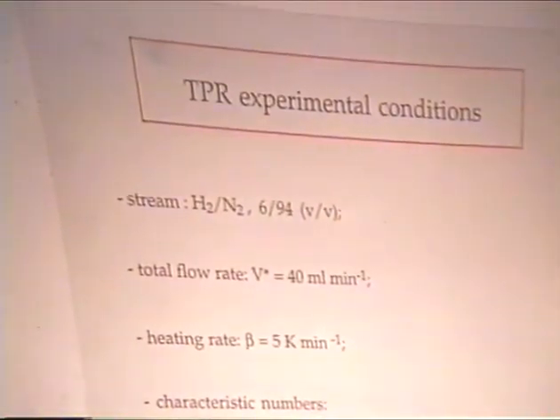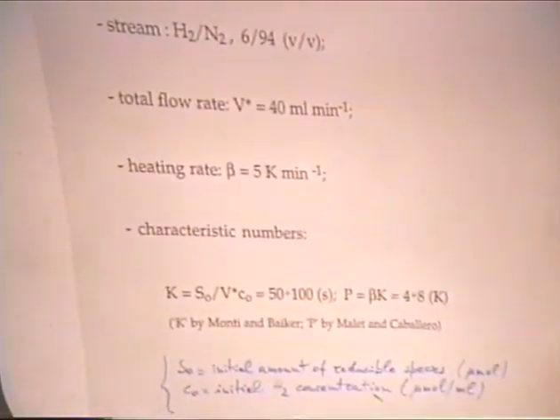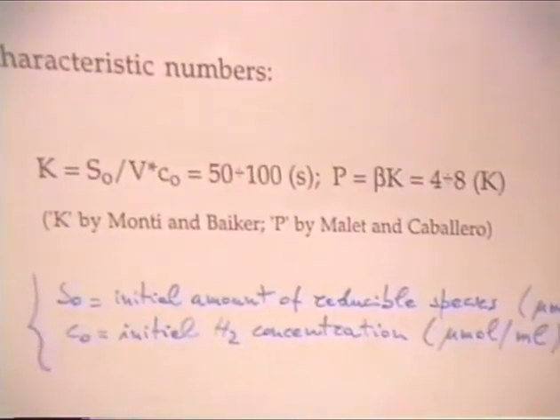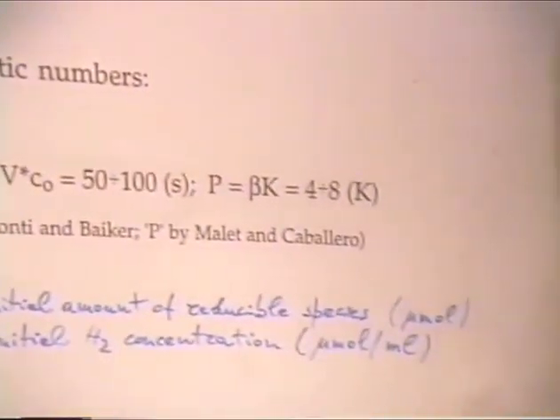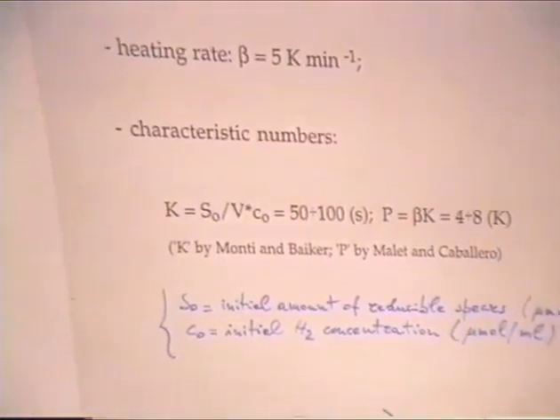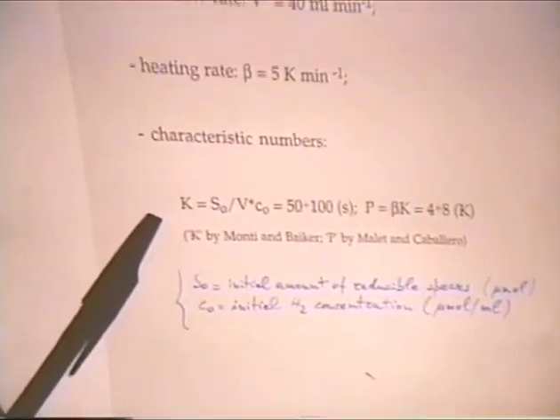So also in this case, our aim was both to evaluate the reduction behavior of this kind of catalyst, and to check the presence of a synergistic effect between the oxidic phases in the mixed oxide catalyst. In order to do this, we carried out a TPR investigation using a diluted stream of hydrogen and nitrogen. In order to obtain optimum reduction profiles, the experimental operating variables were fixed by setting adequate values of the K and P parameters, which were introduced in the literature by Monti and Baiker and by Malet and Caballero.